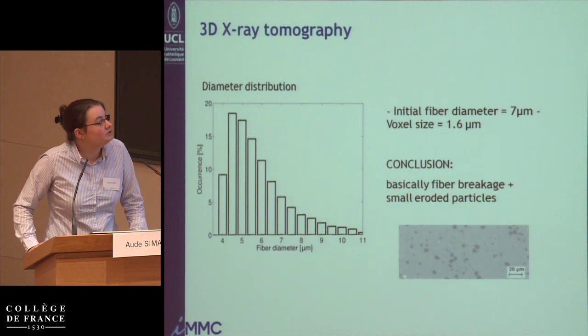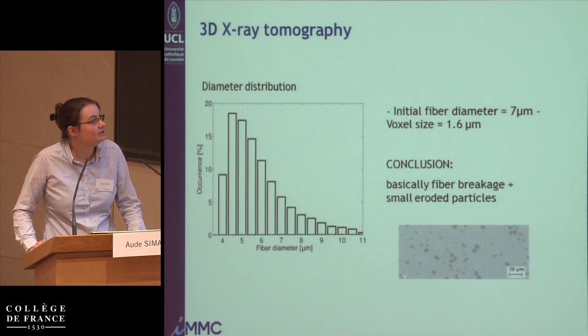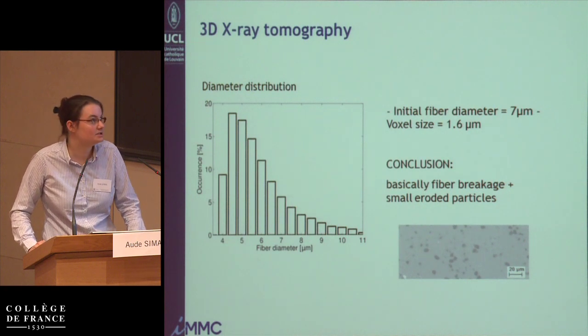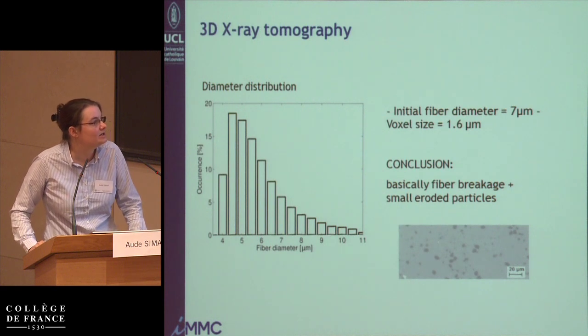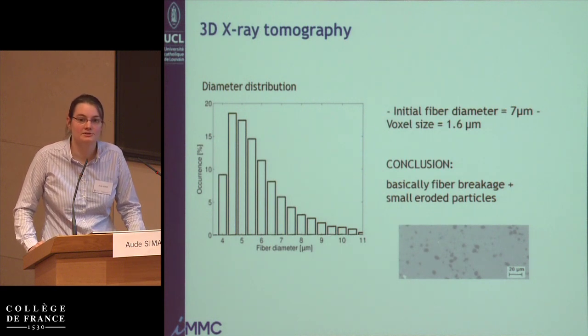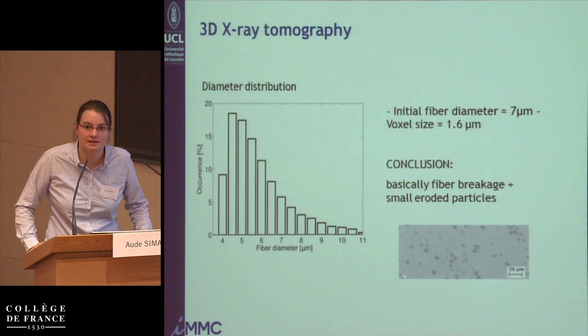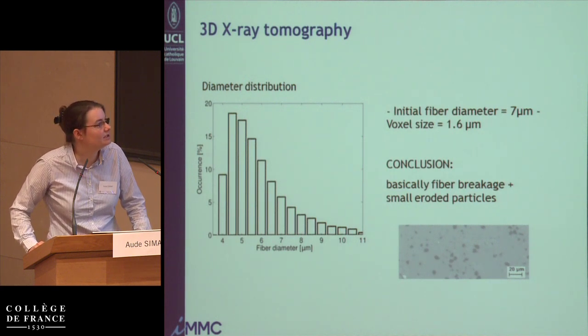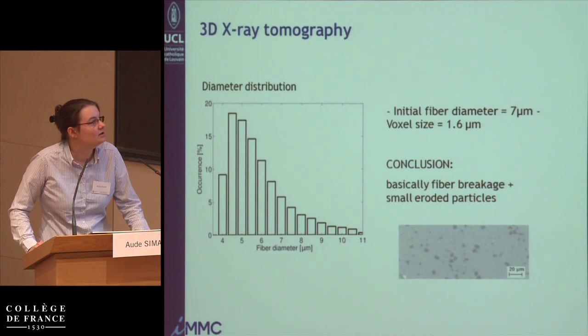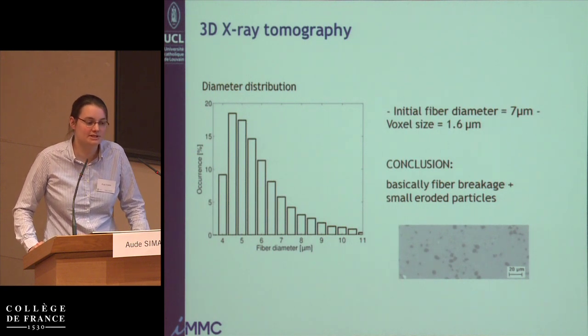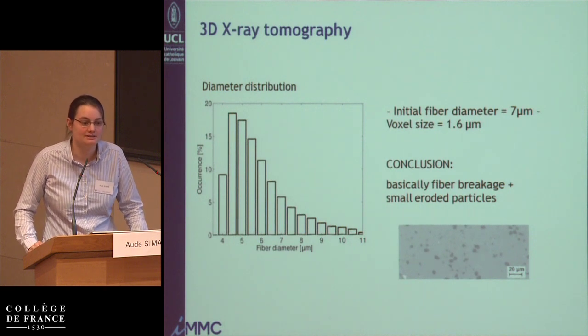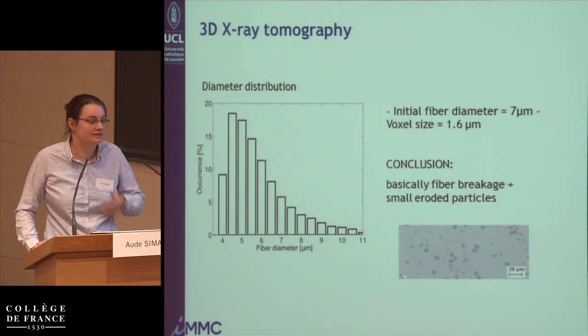So just looking first at the diameter distribution that we obtained by X-ray tomography, the initial fiber diameter was 7 microns. Just to mention that the voxel size was 1.6 microns, so this explains why you shouldn't consider any observation below 2 microns as being really relevant for the measurement that we're doing here. But basically, you have a little bit of fiber breakage, but the fibers remain as one fiber. They are just broken on their length.